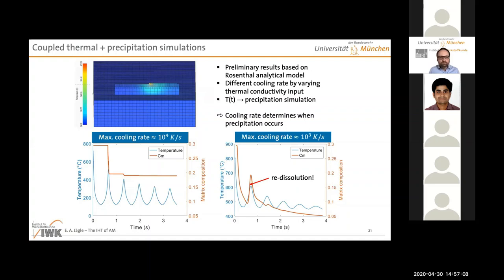But basically, you already have this tool which gives you, not only for your part, but also for your build, which could take into account what you've been describing: different number of parts, different arrangement of parts, even stuff like base plate thickness above the heated bed, modular heated bed. You can relatively easily with commercial FEM solutions take all of this into account. And if you have a kinetic model which works really well, it doesn't need to be appealing for a physicist, but it needs to be computationally cheap, you could easily implement that into such a model and just give you immediately out of the model your hardness profile inside the sample. So that is, I think, a solvable engineering problem.